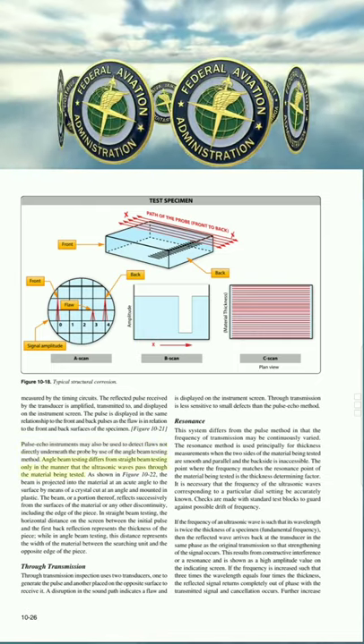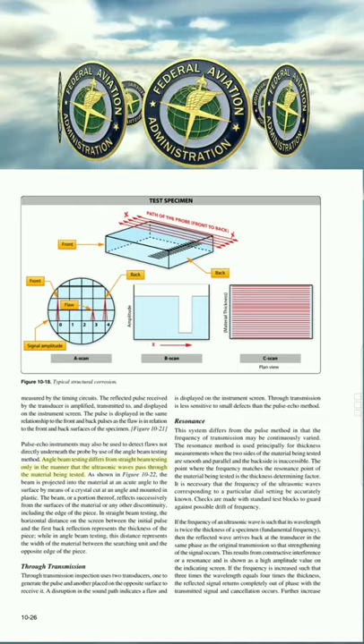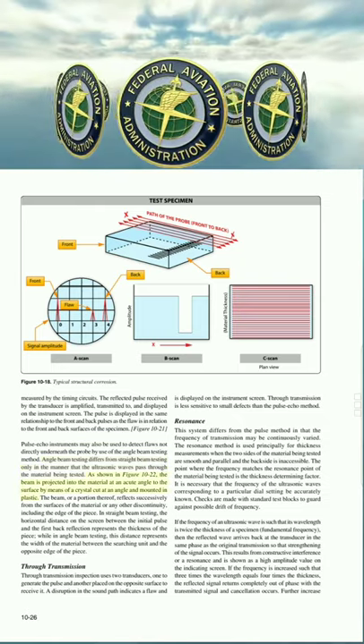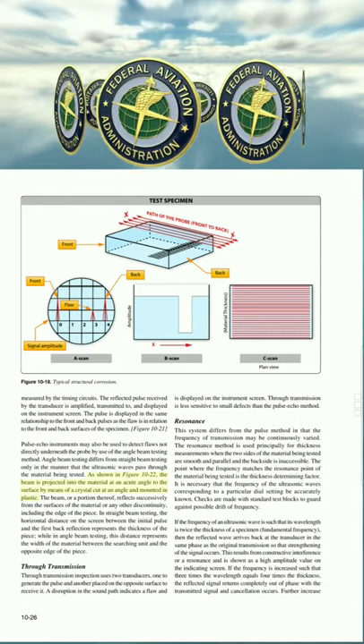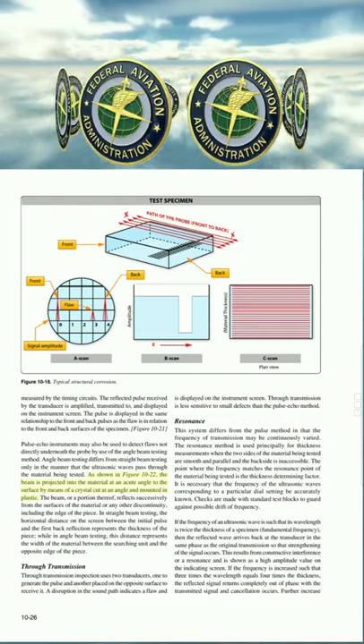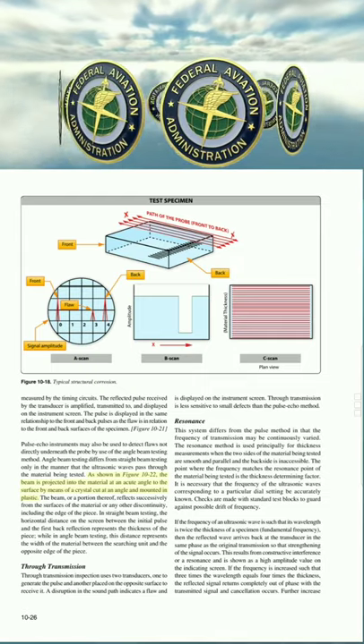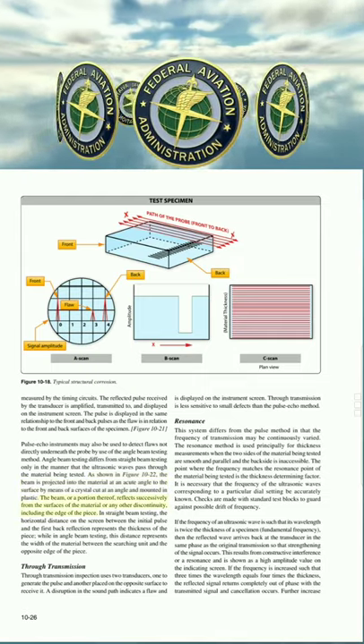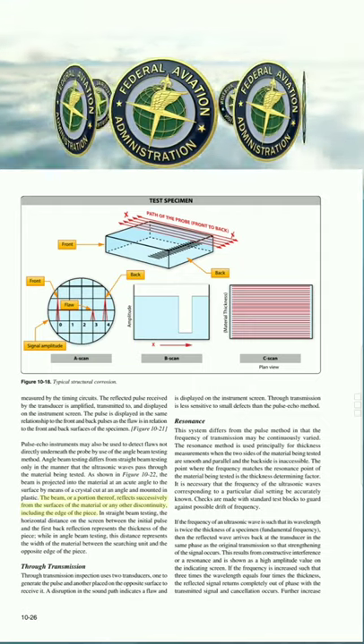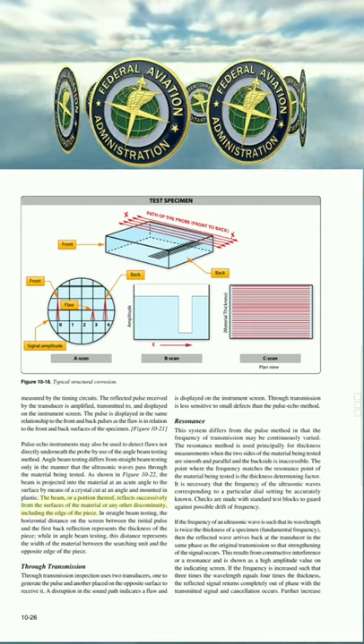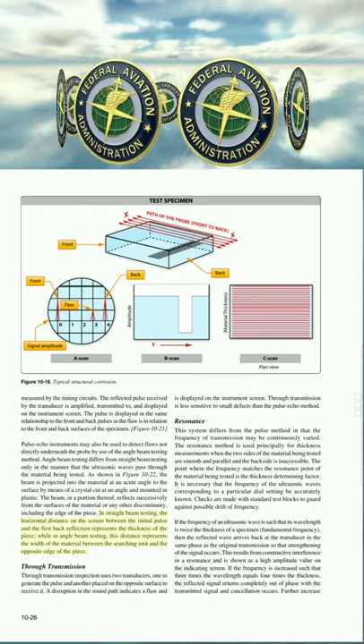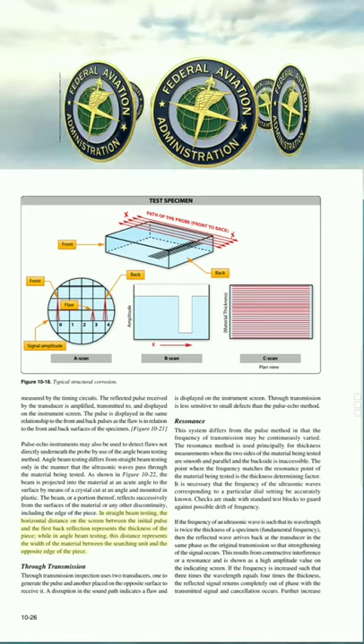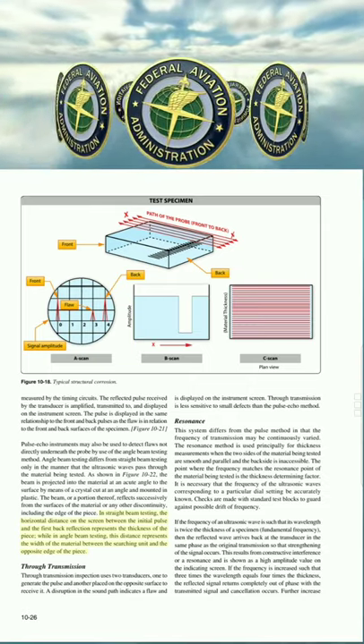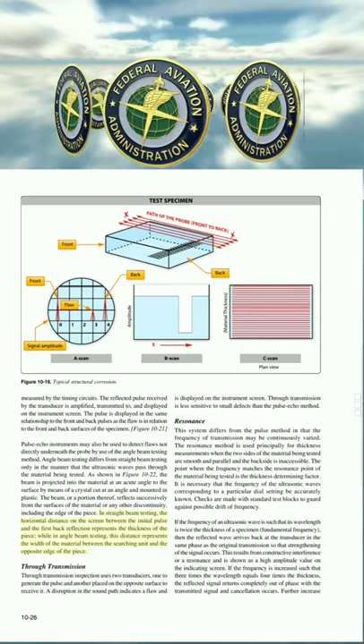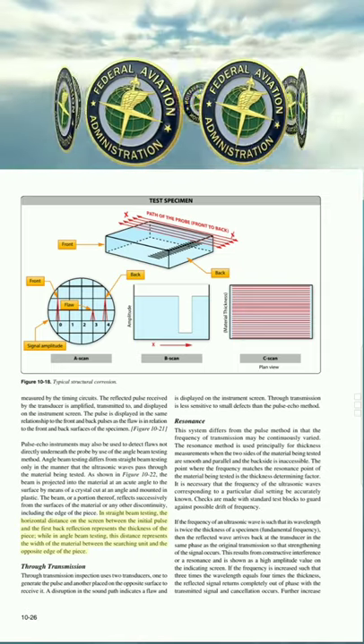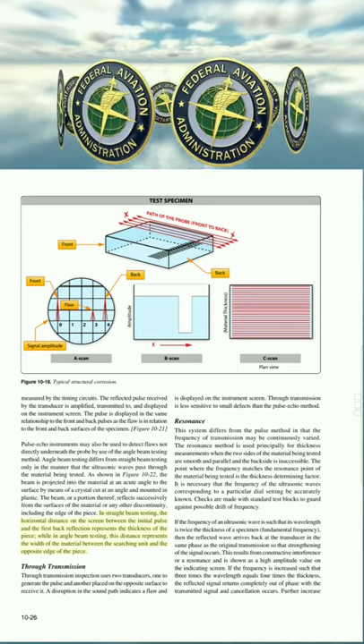Angle beam testing differs from straight beam testing only in the manner that the ultrasonic waves pass through the material being tested. As shown in Figure 10-22, the beam is projected into the material at an acute angle to the surface by means of a crystal cut at an angle and mounted in plastic. The beam, or a portion thereof, reflects successively from the surfaces of the material, or any other discontinuity, including the edge of the piece. In straight beam testing, the horizontal distance on the screen between the initial pulse and the first back reflection represents the thickness of the piece, while in angle beam testing, this distance represents the width of the material between the searching unit and the opposite edge of the piece.